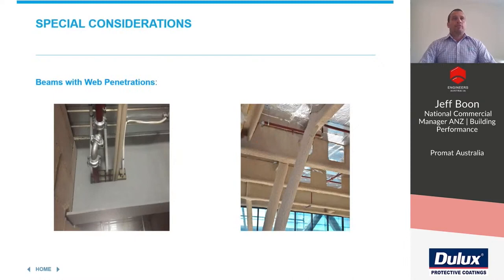Beams with web penetrations. Where a beam has a penetration cut into it for services to pass through, this will affect the performance of the beam. The thickness of the material around the penetration needs to be greater than that for the rest of the beam. There is a method to calculate this in AS 4100. The increased thickness should extend for 300mm on all sides of the opening, or to the full depth of the beam if it is less than 300mm. If a beam is in line with a compartment wall, then the opening and the services will need to be fire stopped to maintain the integrity of that compartment.